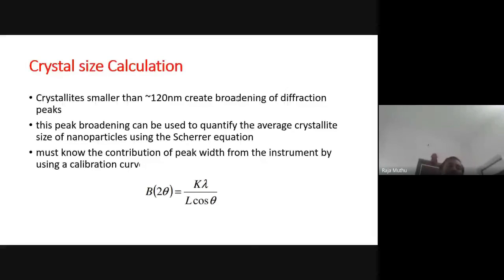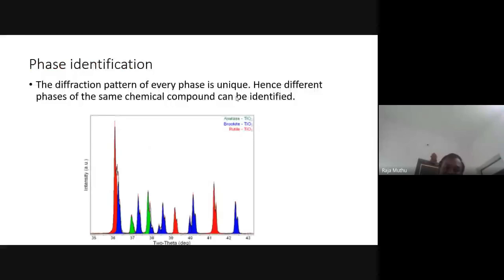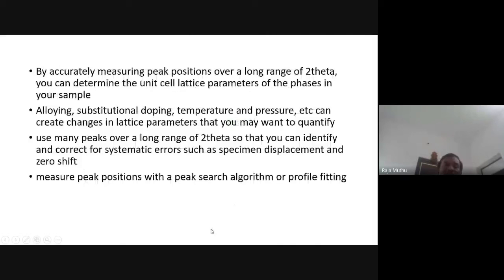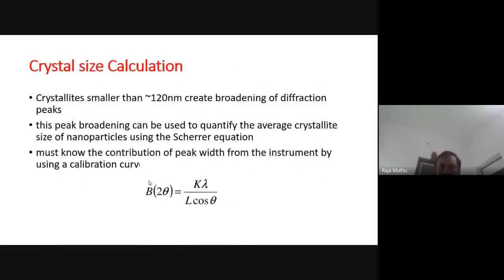Crystallites smaller than 120 nanometers create broadening of diffraction peaks. Diffraction peak broadening, what is it? You can see it in the red line. This is the broadening of the peak. The broadening of the peak depends upon the crystal size. If the size is less than 120 nanometers, it creates broadening of diffraction peaks. This peak broadening can be used to quantify the average crystallite size of nanoparticles using the Scherrer formula.